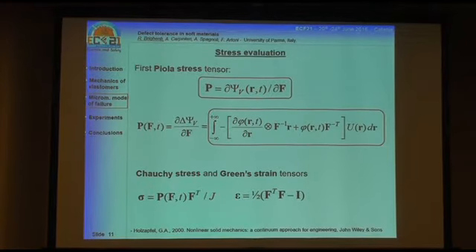Finally, if we want to get the stress, for example, from standard finite elasticity theory, we can get the first Piola-Kirchhoff stress by deriving the mechanical energy with respect to the deformation tensor. We can get the complete expression, which is again an integral over the chain end-to-end distance vector r. And finally, if we want to have the Cauchy stress or the Green strain, we can easily find it by using the stress obtained this way.